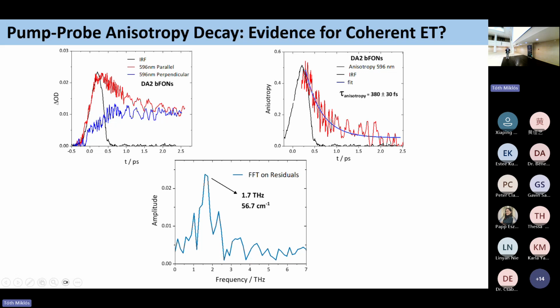And moreover, we also tried to give an interpretation to this oscillation we see in the anisotropy track, and by applying a fast Fourier transform on the residuals from the fitting, we have found a major peak in frequency at 1.7 terahertz that corresponds to an energy of about 56 cm^-1, that could maybe account for some vibrational coherence that derives from the fact that the dyes are very tightly packed in the particles, so they are maybe in a strong coupling regime. But those data are preliminary and for sure need a better evaluation.